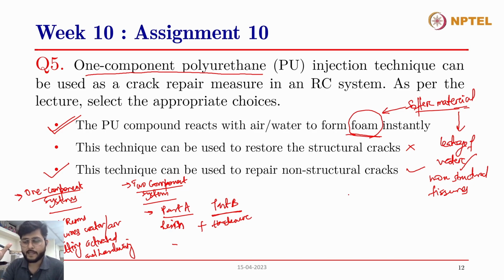They fill these cracks and then come out once this PU system is effectively injected inside the cracks. So if they completely fill the cracks, they will come out, so that we'll know that the crack is totally filled. But these are only temporary systems, and they can only fill the cracks temporarily, like they can stop the leakage of water temporarily, and then again we have to carry out an injection using epoxy, because epoxy is a harder material.